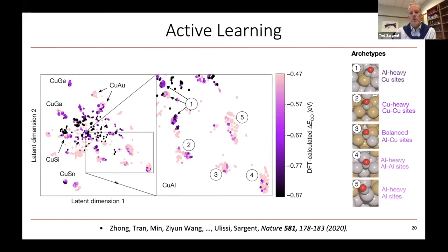So we were then able to really dig in and dive into these adsorption sites. You can see that if we zoom in on the copper aluminum region, we were able to look at the chemical character of some of the best sites that had the adsorption energy of around minus 0.67 eV. You can see that that's this mid purple color. And you can see that archetype number one, labeled with these various arrows, is showing a lot of near optimal adsorption energies.